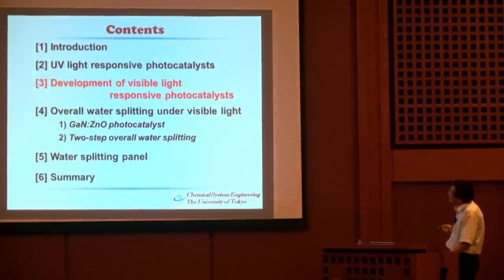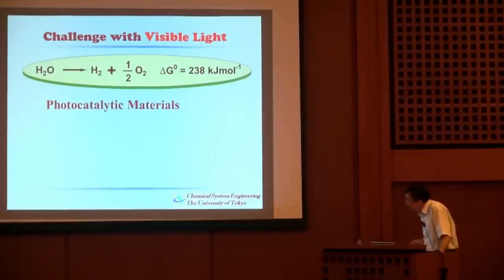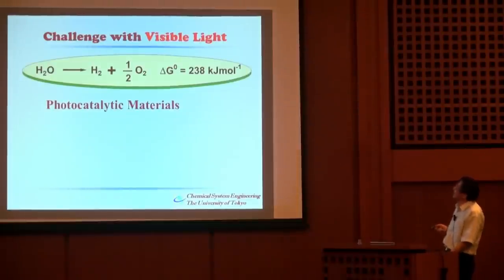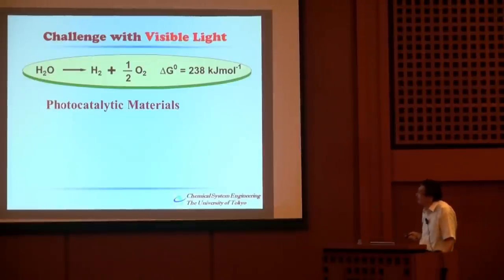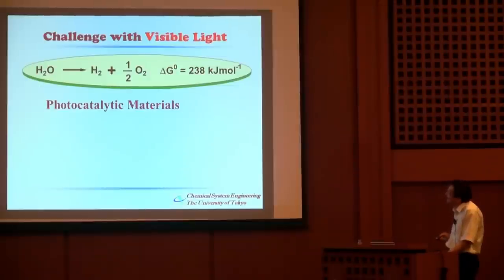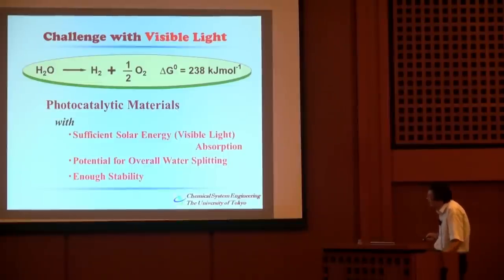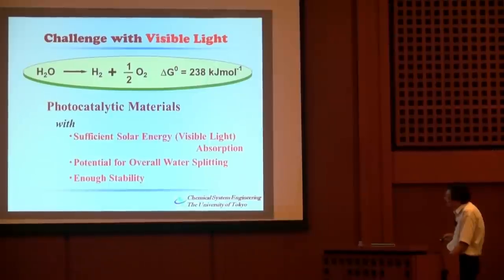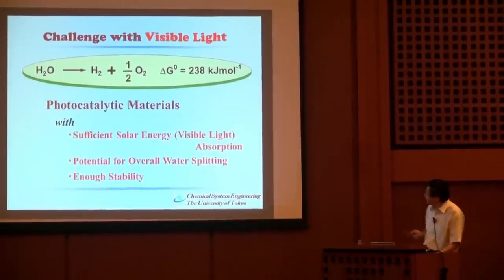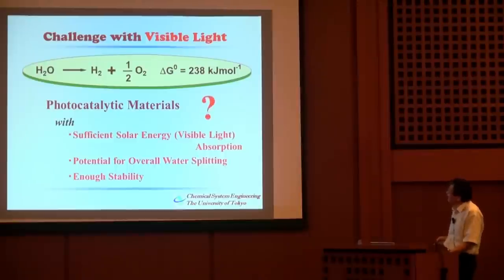Now let me move to the development of visible light-responsive photocatalysts. To efficiently utilize solar energy, we need photocatalysts that work under visible light irradiation. New photocatalyst materials must meet three conditions: absorb visible light, have band positions suitable for water-splitting, and be stable during water oxidation or reduction. It is very difficult to find materials satisfying all three simultaneously.